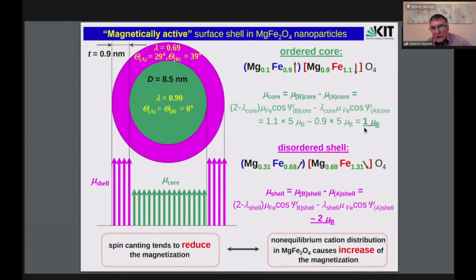calculations give us one Bohr magneton for the core of nanoparticles, and for the shell, if we take the values from Mössbauer spectroscopy, we obtain a value 2 times higher. That means we have a magnetically active surface shell in magnesium ferrite nanoparticles.